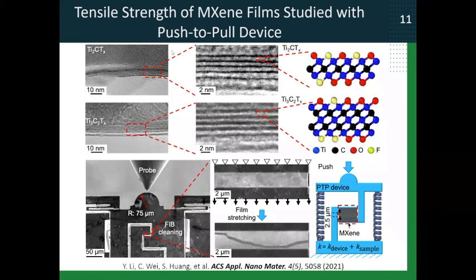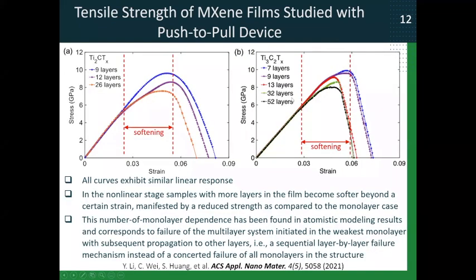And here I show it for two different MXenes, titanium 2C and titanium 3C2, and different numbers of layers. So all curves demonstrate a similar linear response at the beginning, which we can use again to calculate Young's modulus. But then we observe a non-linear stage, and the samples with more layers become softer beyond a certain strain, of course, and that limit after which they become softer depends on the number of monolayers. Okay, so I'm talking about this part of the curves now. When it starts to deviate from linear, this is the softening phenomenon, and you can see that all samples demonstrated it, and the extent to which they demonstrated it depends on the number of monolayers.